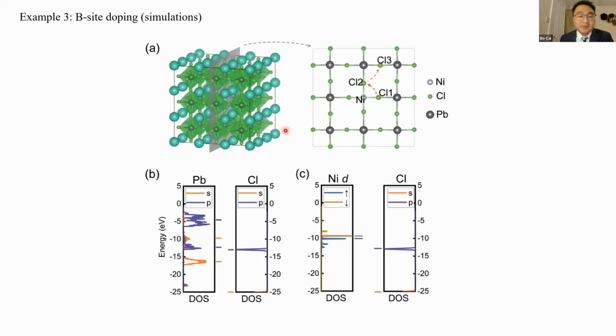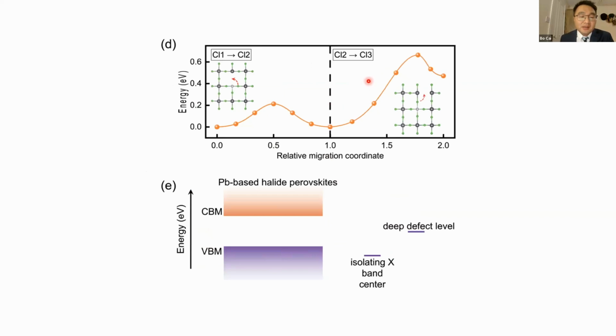This is the third example. We try to suppress the ion migrations in lead-based halide perovskites. We introduce B-site doping strategies. The second example told us that transition metals might work well for these systems. So we design a nickel doping system, and the migration pathway is like this. Similar results: there exists a good match between nickel and chlorine. So we think the barriers should be high, and the CI-NEB result agrees with it very well.